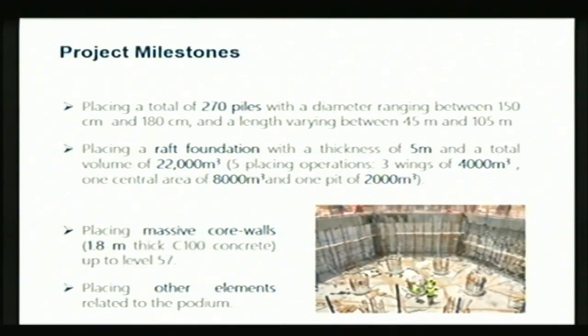Initially, when you have a project like this, you grout the ground. You just inject grout to make sure you fill all the cavities even before you start the piling. You really reinforce your ground with the grouting before you do anything else. And then you had 270 piles between 1.5 and 1.8 meter in diameter, and the length varied between 45 meter and 105 meter. So the biggest piling machine was on this project to be able to do this kind of pile size. Then it was followed by a raft foundation, 5 meter thickness.